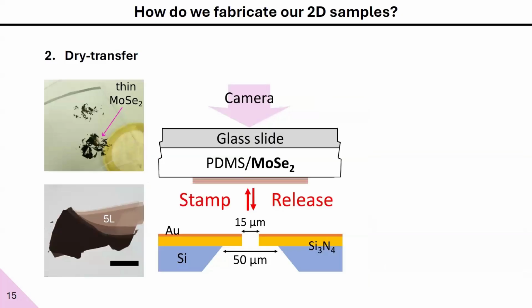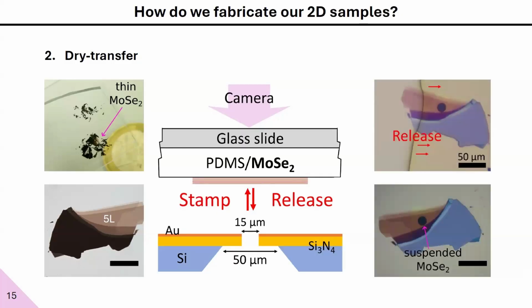We take these flakes, put them upside down, and with the aid of a camera, align them to our substrate. Via a stamping process, we transfer our 2D materials, in this case over a circular aperture, therefore producing a suspended membrane of our atomically thin material. So we make tiny drums.